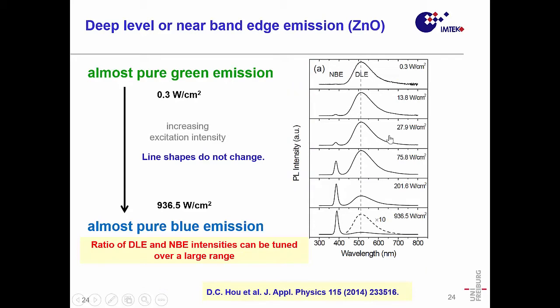There is some confusion in the literature, and that's why I put it in. So if you measure the luminescence for zinc oxide, and it's also the case for other oxides, there are two luminescences which you have. One is coming out from defect states, and the other is coming out from near bandgap emission. And there's very often the statement in papers that if the ratio of the near bandgap emission to the defect emission is rather high, you get a high peak in the near band emission, then the quality of your wire is good. That's not the case. Have a look.